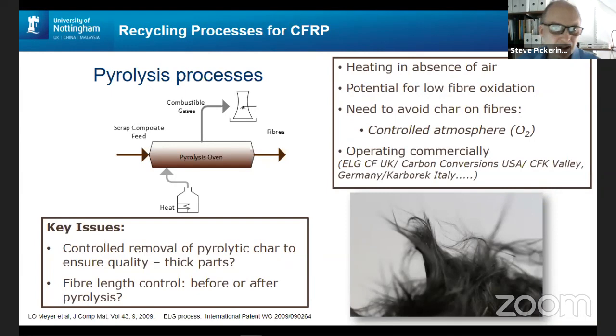The polymer resins will break down by the action of the heat, and leave the fibers behind. Now, the problem when you break down polymers in the absence of air is that you tend to form a pyrolytic char. A char is left behind on the fibers, and this means you can't separate the fibers, and they're difficult to reuse. So you need to have a controlled atmosphere where you can offer a little bit of oxygen to oxidize this char, giving clean fibers. So there's probably more work being done on pyrolysis processes than any other, and there are already